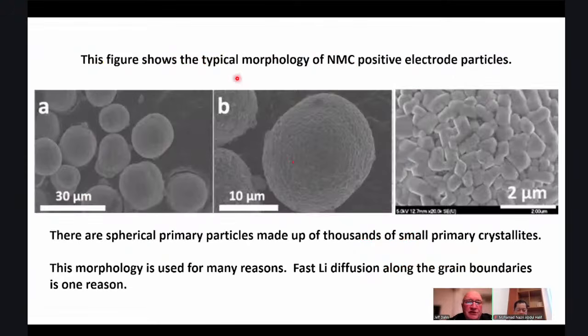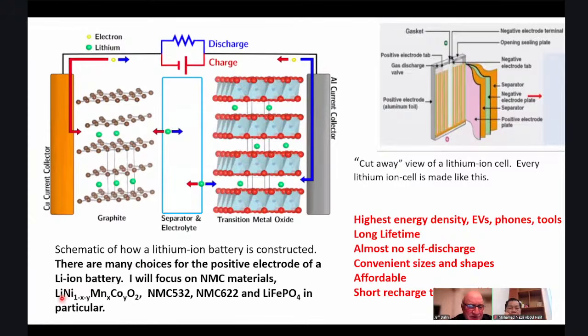So I want to talk about lifetime now of lithium-ion batteries and show you that they are suitable for long-term energy storage and also for what everyone calls vehicle-to-grid operation. So a lot of lithium-ion batteries use so-called NMC positive electrode materials. I forgot to mention that NMC is a lithium nickel manganese cobalt oxide material, and the relative ratios of nickel, manganese, and cobalt are given by these numbers, like 532 means 50% nickel, 30% manganese, and 20% cobalt.